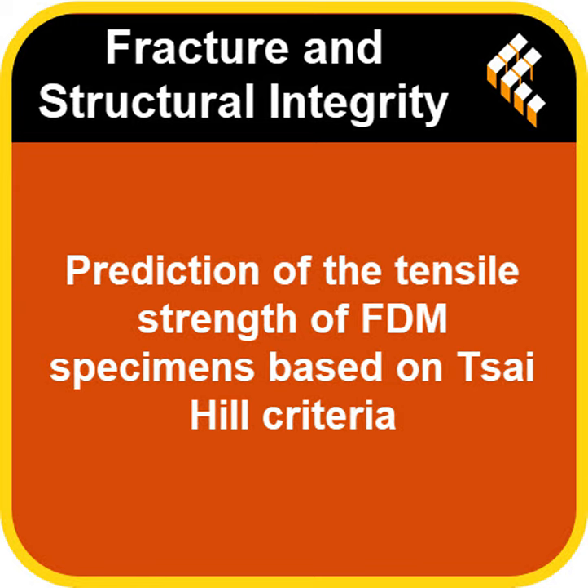Yeah, I think there are a few really practical points here. First off, pretty clearly, if you need maximum tensile strength, pulling strength, align your print lines with the direction of that force. That 0-degree orientation is your strongest bet. Okay, rule 1, align with the force for tension. Rule 2, maybe? Adding that outer shell, the contour, seems to be generally beneficial. It tends to improve both tensile and shear strength, and also the toughness, how much energy the part absorbs before breaking. You said tougher overall. Yeah, it seems to enhance the layer adhesion and provide some extra structural confinement. So unless there's a strong reason not to, using a contour looks like a good idea for mechanical parts. Good default setting, maybe? Perhaps.